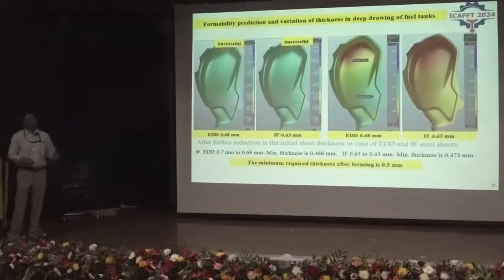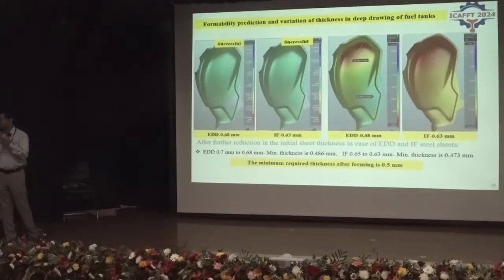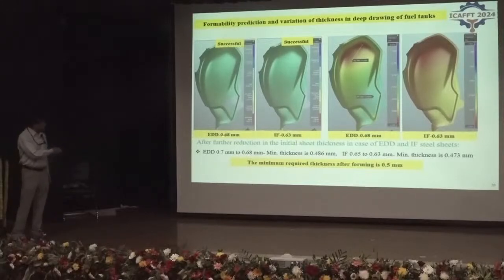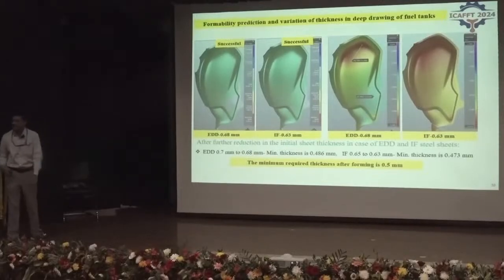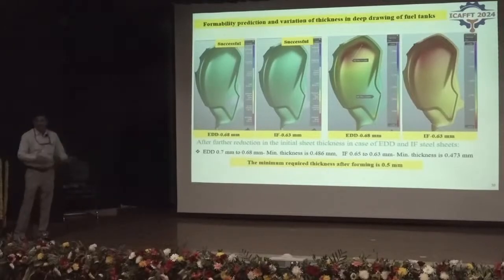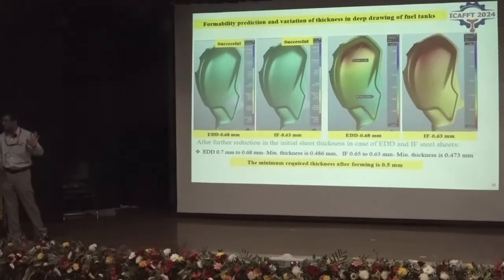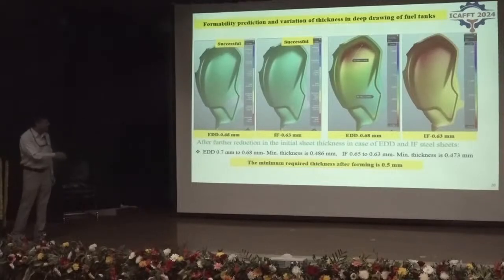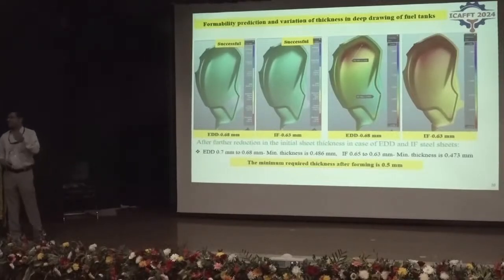So now, just to explore what is the minimum possible thickness, we went down to 0.68 mm in the case of EDD and 0.63 mm in the case of IF steel. At that time, we have seen that the parts can be successfully formed without any problem. But the only thing is, thinning was more than what can be tolerated.